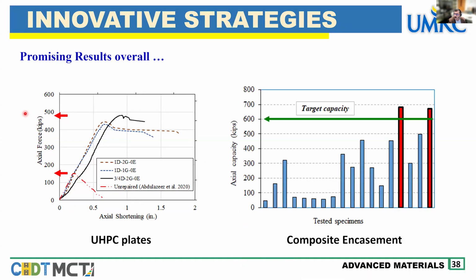Now with the composite material, the jacketing system using the CFRP and also the concrete infill, the squash load for the healthy section without any corrosion is 600. With the repair, using the composite encasement for the corroded damaged column, with the CFRP, the concrete infill and also the headed studs as a mechanical interlock, we were able to reach up to 700, more than the load of the healthy section without any corrosion. And this is the advantage of using the advanced material in the whole retrofit method.